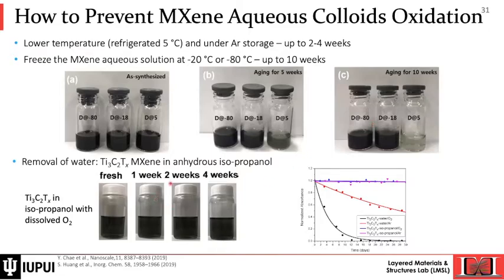Also, the other way is just to remove the water. If you remove the water, you can see that in this study, it showed that if we disperse MXene in isopropanol, even if we have oxygen, they're stable. And you can see here that this is MXene in isopropanol with oxygen, that up to 30 days, there is almost no change of properties. So that's another way to control MXene oxidation. Change the solution from water to isopropanol.